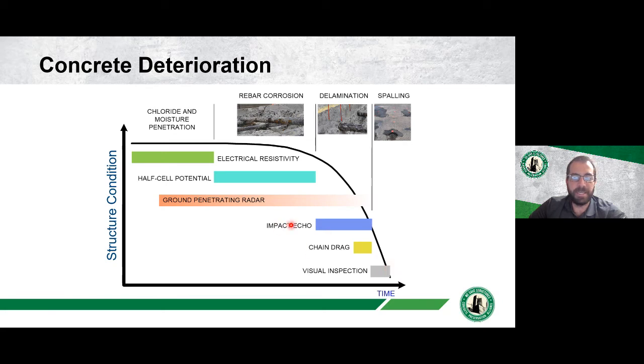If we use things like impact echo, we can better identify delamination sooner than, say, with chain drag. Ground penetrating radar can identify a lot of different conditions, and so we can identify maybe rebar corrosion with, say, half cell or GPR, or chloride and moisture penetration with some of these other methods, sooner so that we can address the condition before it gets to delamination. In addition, all of these conditions are happening simultaneously on a structure.